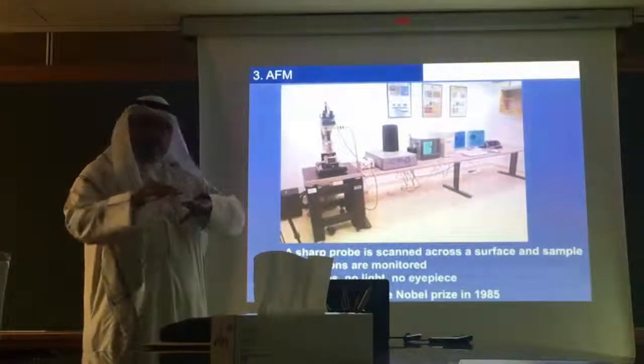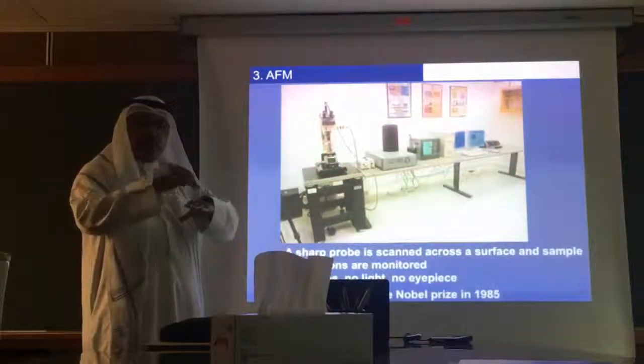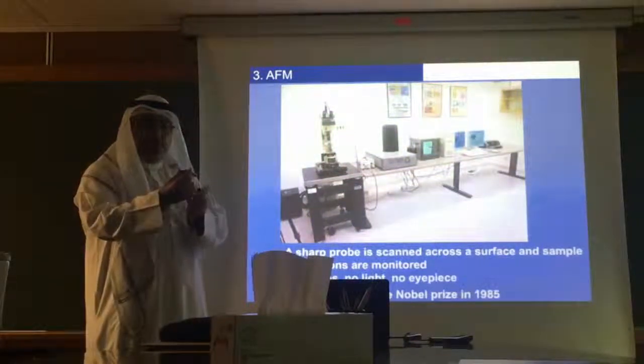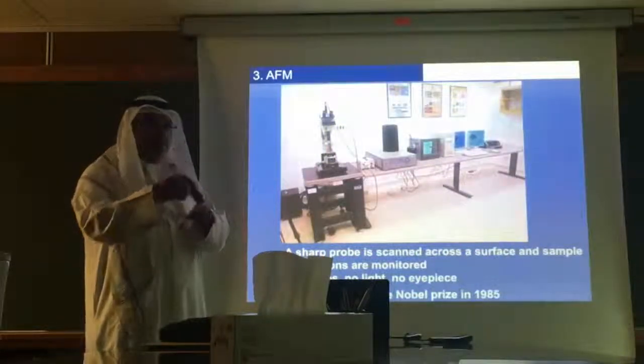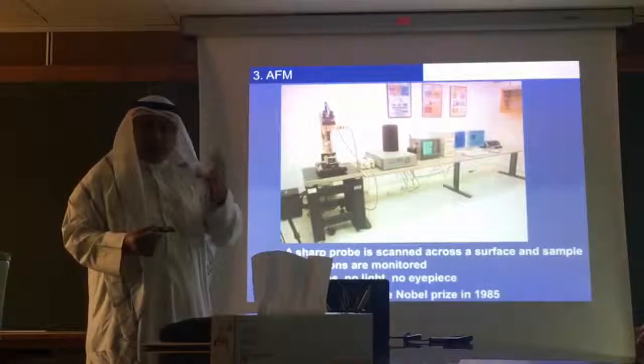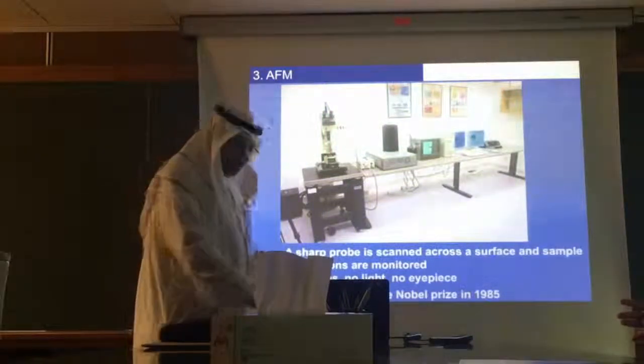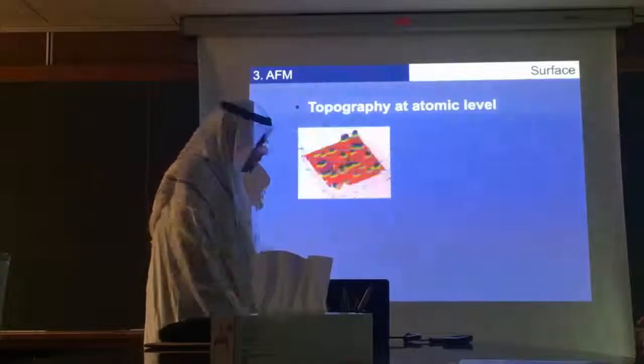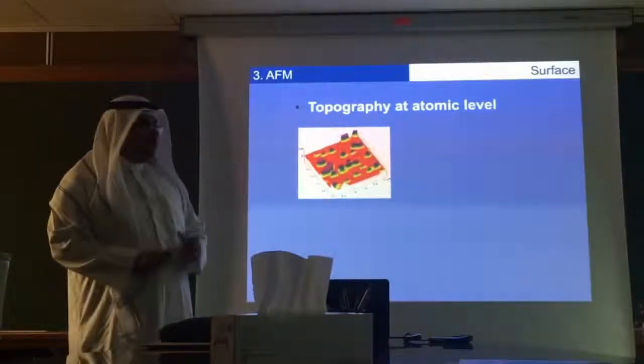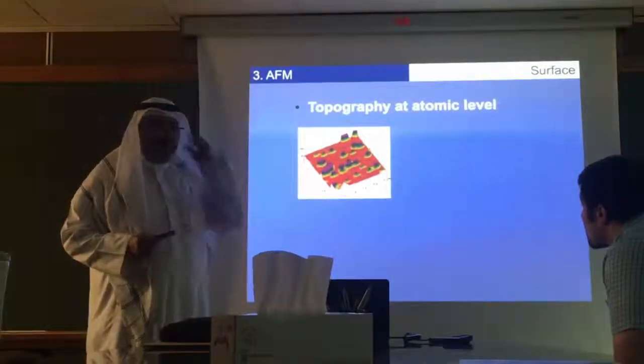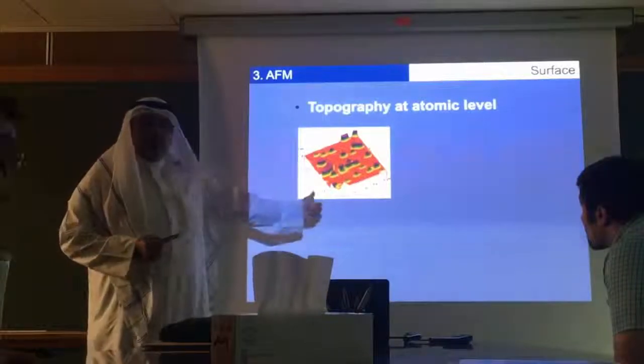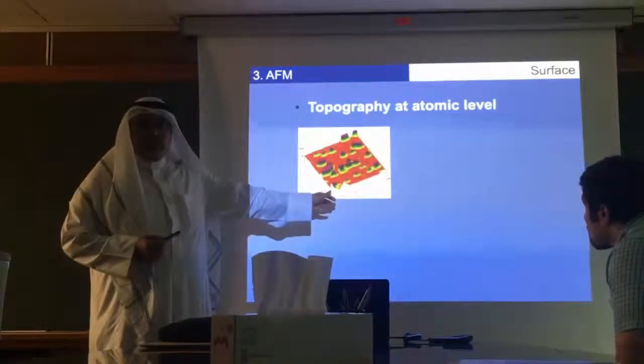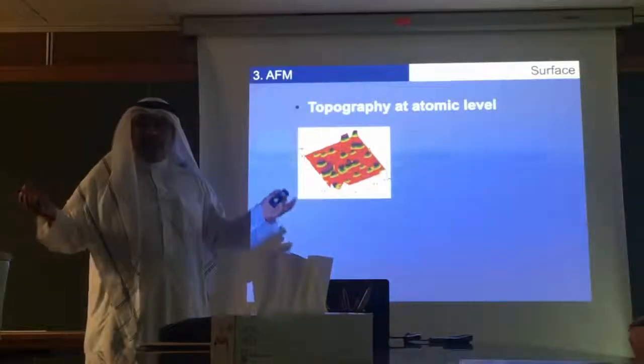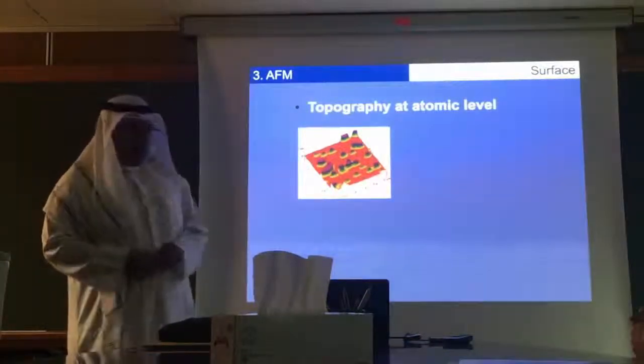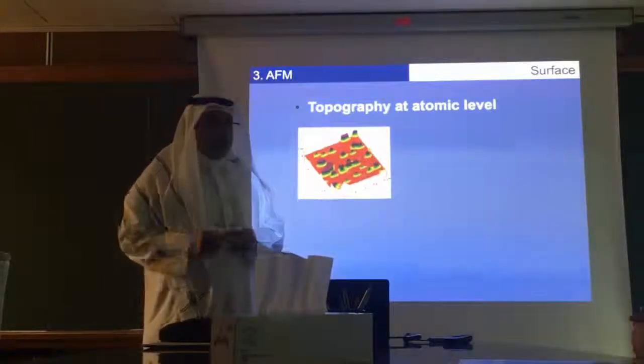And then I scan my sample with the tip. Because of the topography, and there is a spring holding the cantilever from one side, it will shift down and up, and by this shift, it will reflect the laser at a different angle. And from that, we can study the topography. You'll get a plot something like this, and you know how rough the surface is. We think that, for example, human hair is very smooth. But if you put it under an AFM microscope, you can see it like the Himalaya mountains going up and down. These details, you cannot see by just a normal microscope.